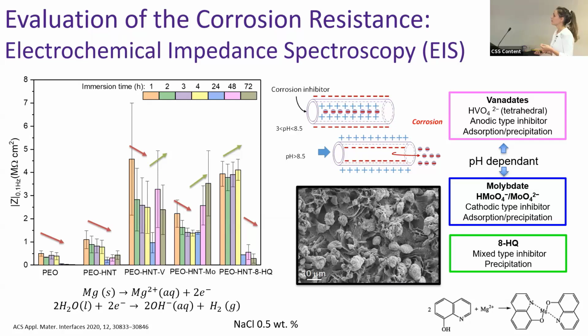Yes. If you look at all the graphs, you can see that we have two behaviors, the first 4 hours and then after 24. So probably the barrier properties of the coating itself is the one that lasts 4 hours for all the coatings. After 4 hours, the electrolyte penetrates through the coating, reaches the magnesium, and that's when corrosion starts. In the case of the coatings without inhibitors, corrosion starts and the corrosion resistance drops. In the case of coatings with inhibitors, corrosion starts, magnesium corrodes, and there is an increase of pH as a consequence of the cathodic reaction. So we don't see the increase in the corrosion resistance until magnesium starts corroding. That's when the pH increases and triggers the release of the inhibitors. Yes, okay. Yeah, thanks.